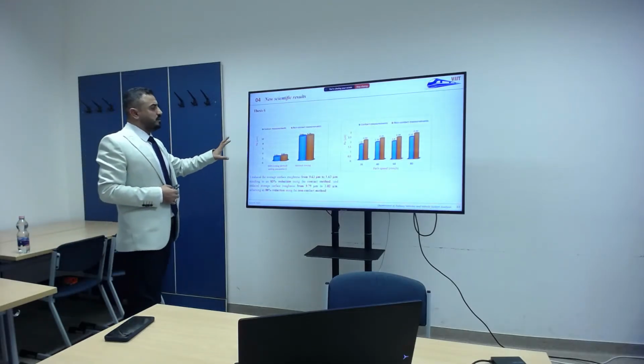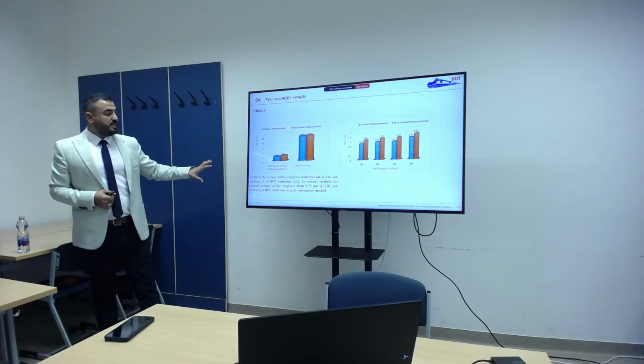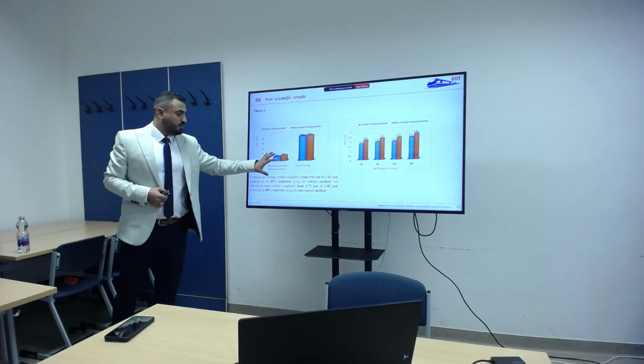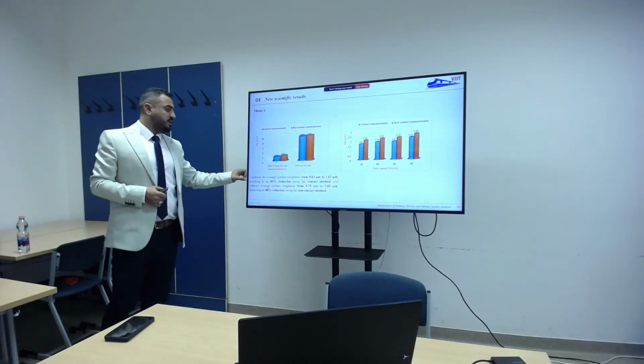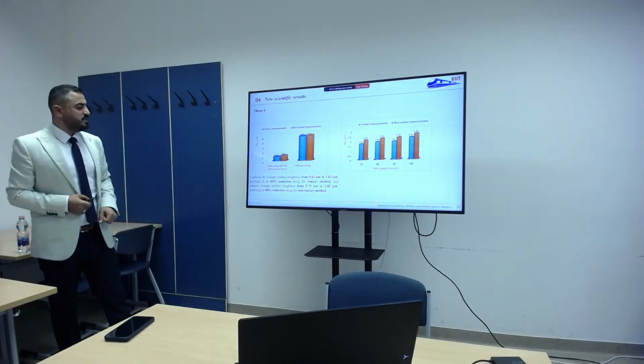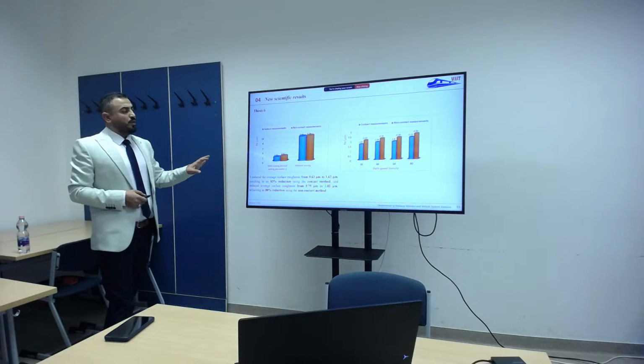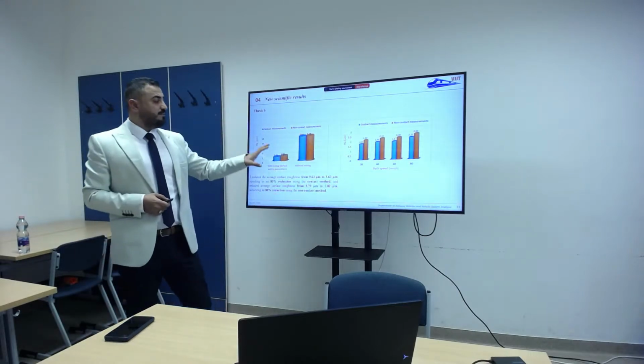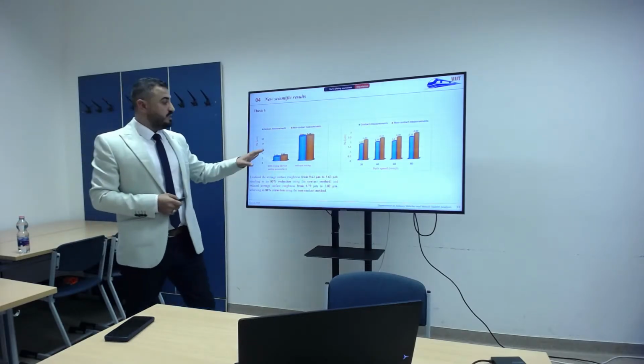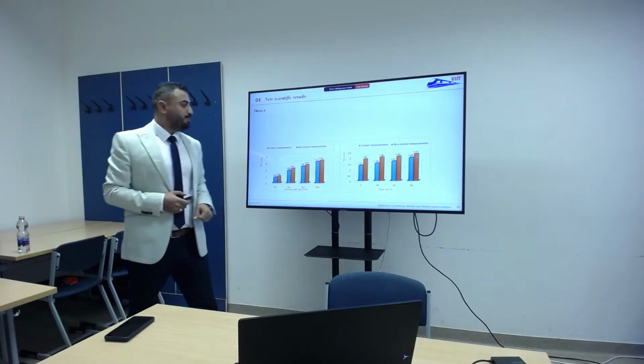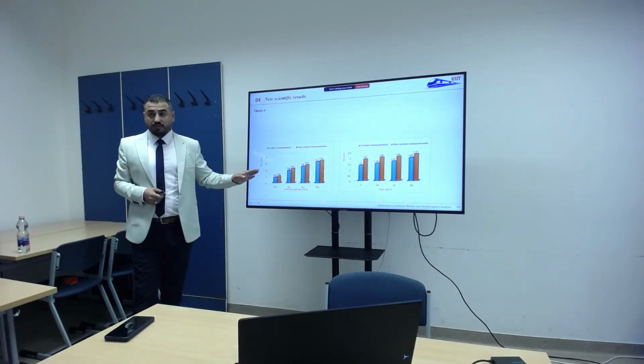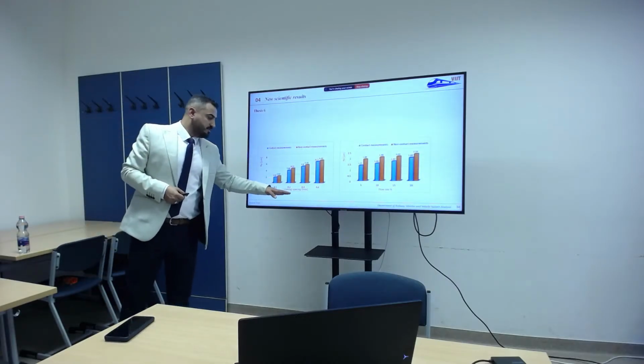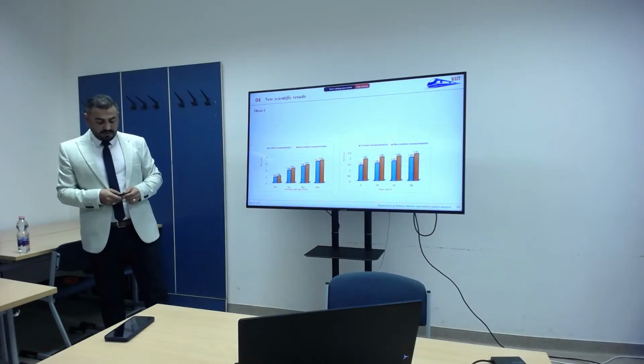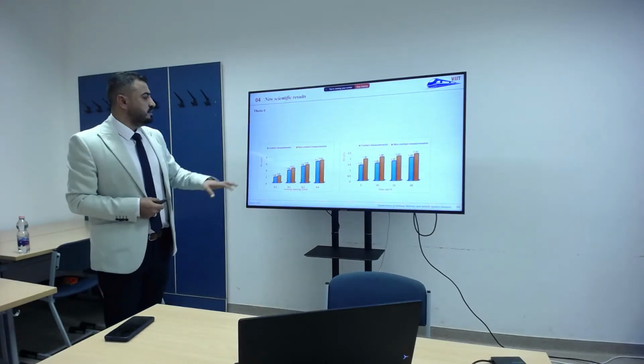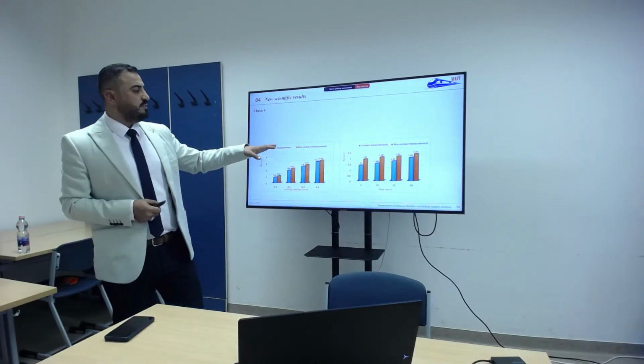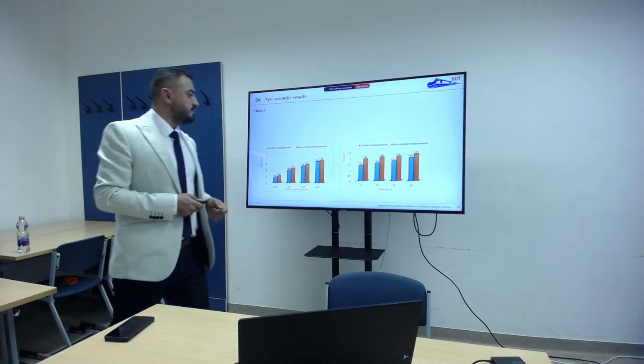Applying the ironing post-processing with the default setting, I minimized the surface roughness by about 83% with the contact method, and I successfully optimized with the non-contact measurement method, about 80% reduction. For each parameter independently, I found that the path speed was slightly positively correlated with the value of average surface roughness. For the ironing spacing, I found it strongly positively correlated with the average surface roughness. For the flow rate, I found that it's slightly positively correlated with the surface roughness.